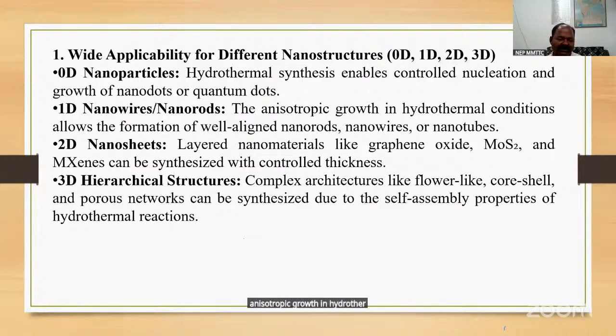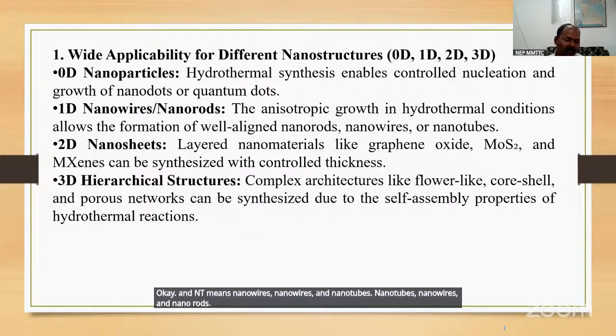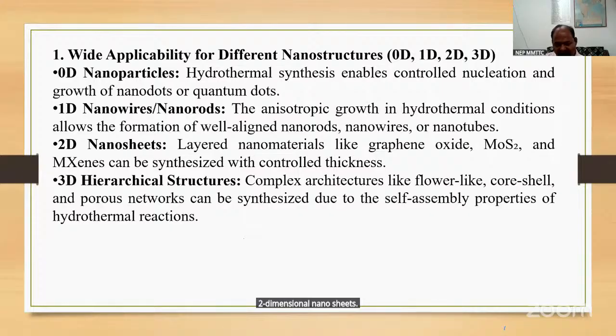Anisotropic growth in hydrothermal conditions allows the formation of well-aligned nanorods, nanowires, or nanotubes. Okay. NR, NW, and NT mean nanorods, nanowires, and nanotubes. Two-dimensional nanosheets, such as graphene oxide and molybdenum disulfide, can be synthesized with controlled thickness. Three-dimensional hierarchical structures: complex architectures like flower-like, core-shell, and porous networks can be synthesized due to the self-assembly properties of the hydrothermal reaction.